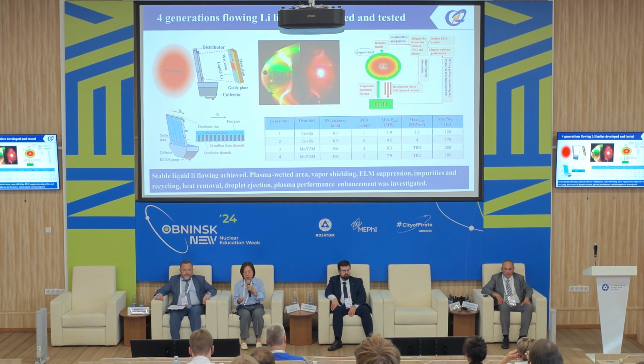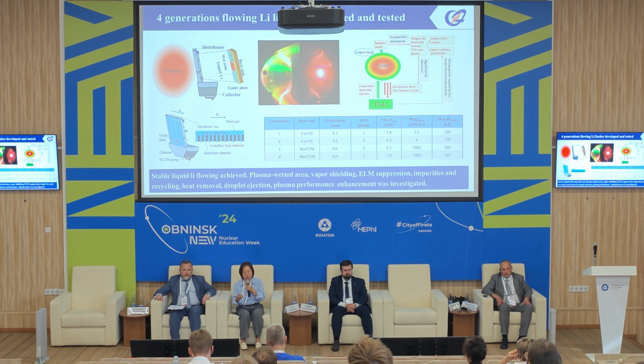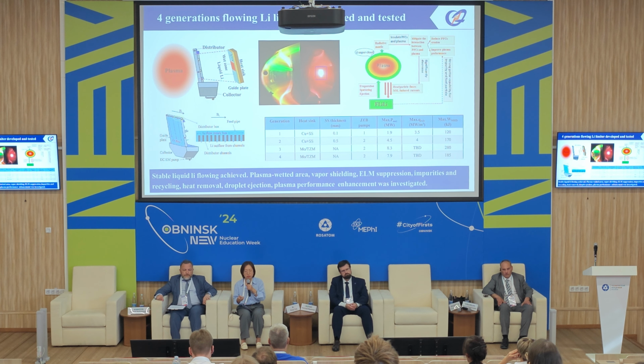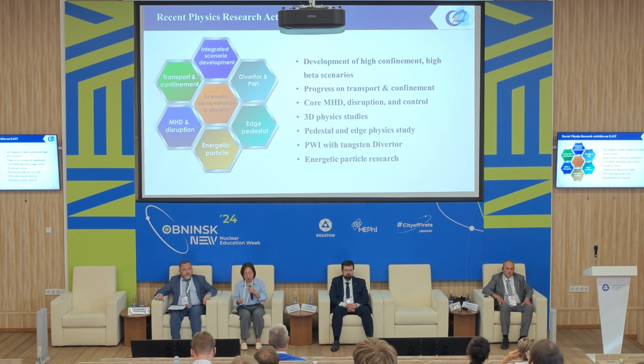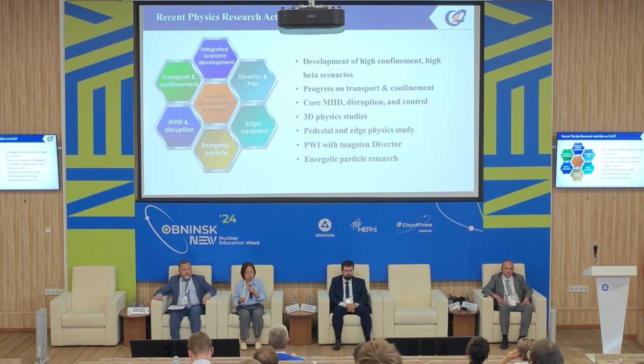Another interesting point is the lithium. In the EAST tokamak, we use lithium coating before plasma discharges, and we have also developed the lithium limiter technology, the flowing lithium limiter technology, to test the characteristics of this material as a plasma facing material. So now the 4th generation has been finished. And the plasma-wetted area, the vapor shielding, impurity, and recycling with this technology have been investigated in the plasma experiments. I introduced some technology developed on EAST tokamak.